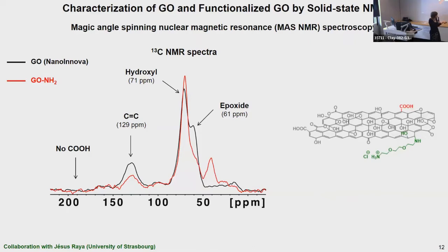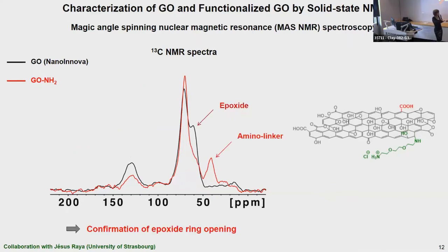You can see here that in this area, there are no peaks corresponding to the carboxylic acids. After the reaction, we can see first peaks appearing here corresponding to the CH2 of the amino linker. And most importantly here, a decrease of the peak corresponding to the epoxides, confirming the epoxide ring opening.